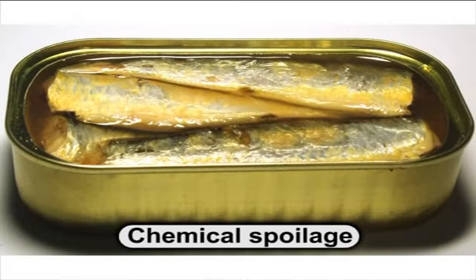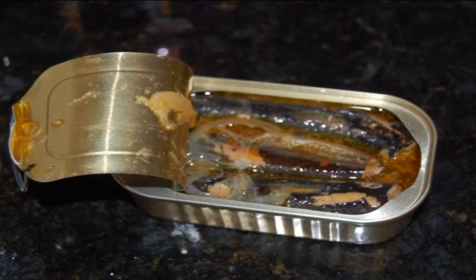Chemical spoilage is caused by the leaching of compounds and or metals from the can walls into the product. Leakage of iron sulfide or FeS from the can into the product causes black discoloration of meat. Lining the can with carbon enamels or addition of parchment paper liners between the product and can eliminates this problem.